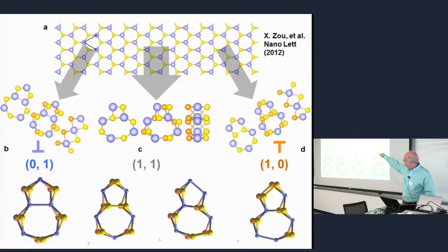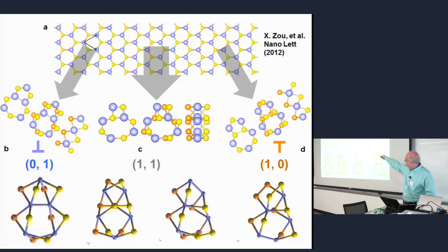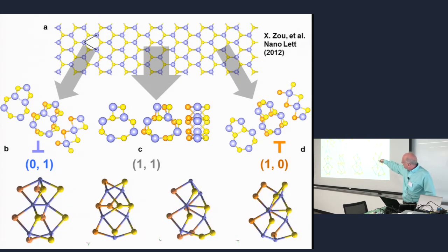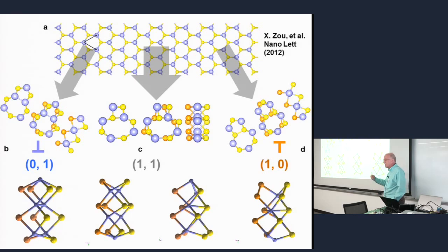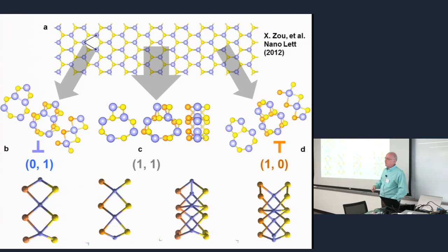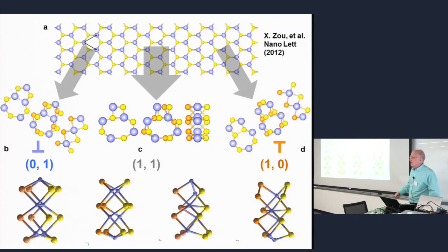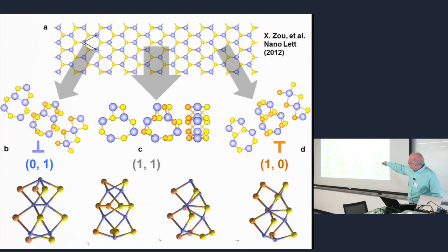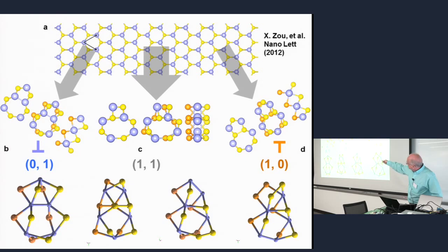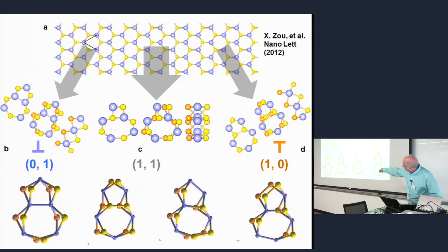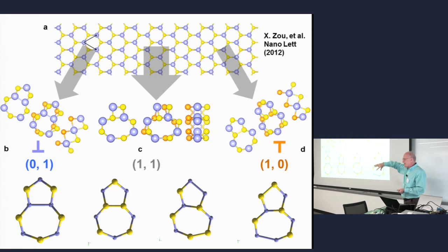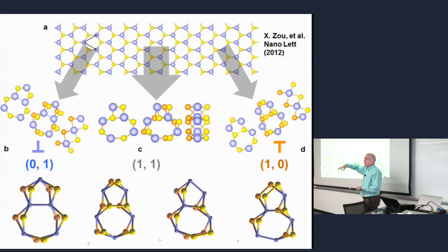And if you stare at it, you see, yes, there is a grain boundary because there is a change in angle, but you barely can figure out anything. So then I gave up and we decided, okay, let's just design them following the rules. You take a lattice, you remove a half crystal plane, a half atomic line, and you relax it. You relax it using density functional theory if you want to be precise, or you can use now-available tight binding, or something. It's not so important, but with density functional theory in this case, after relaxation, you find a structure like this. These animations just help you to see that they are three-dimensional objects.